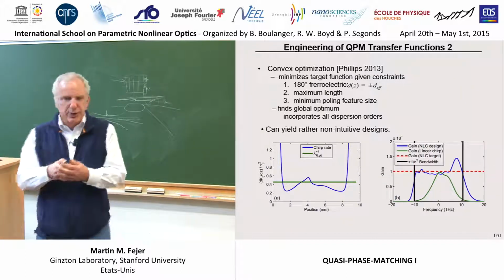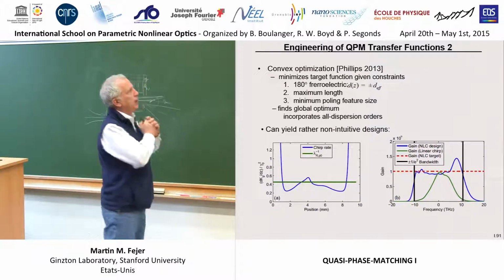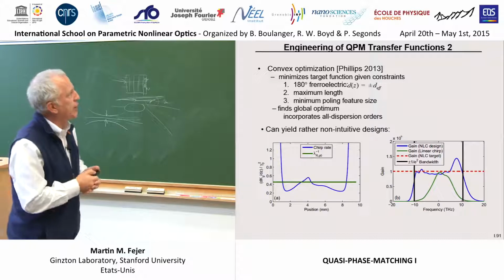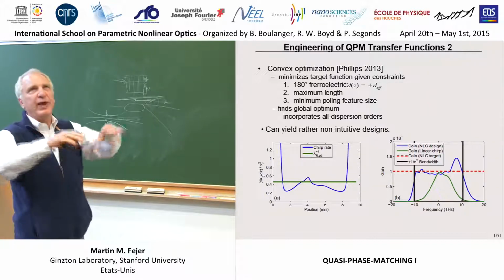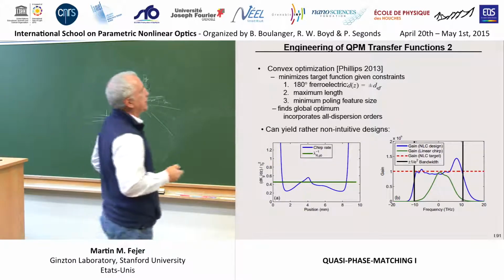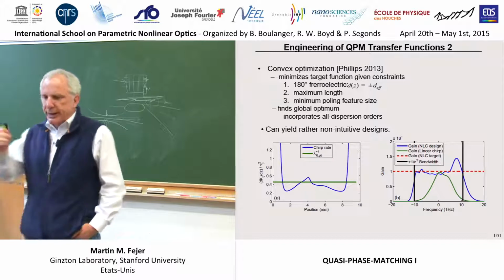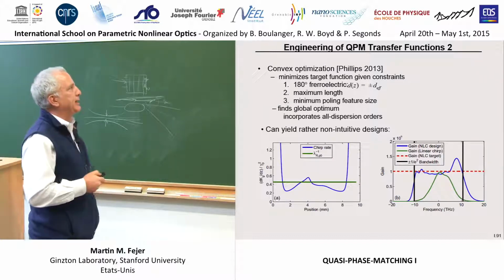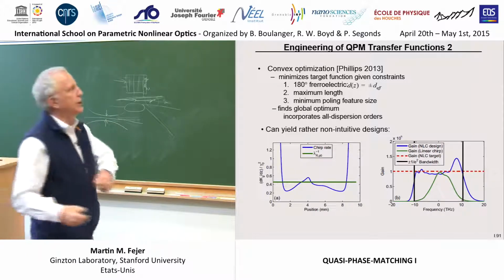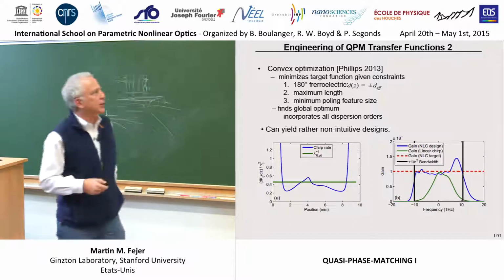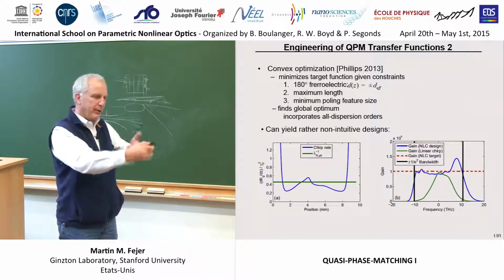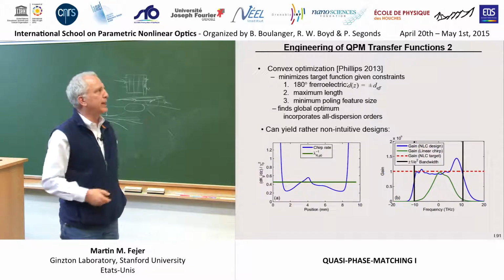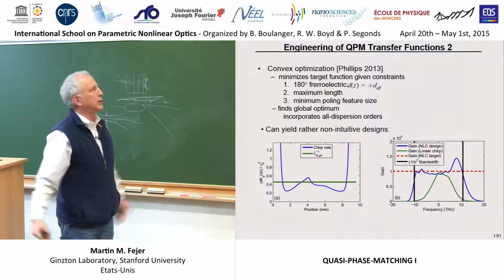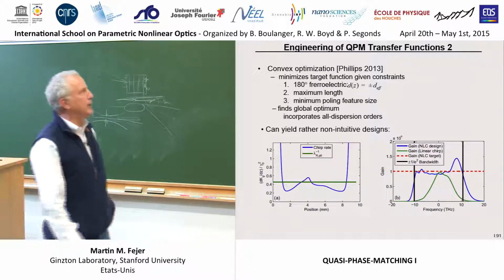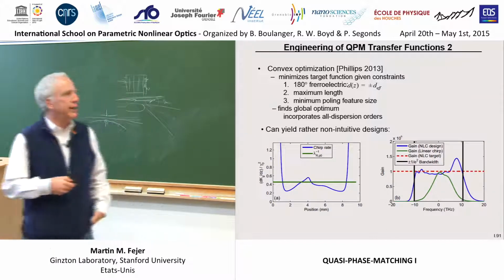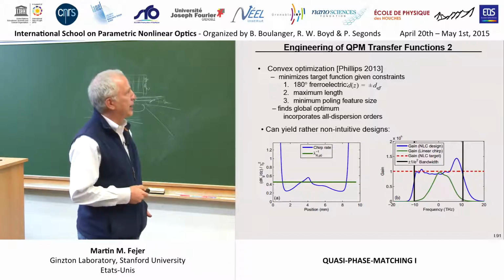Chris Phillips, who was a very good student who graduated from my group a couple of years ago and is now a postdoc with Ursula Keller, he showed that you could actually convert a large family of these grating design problems into ones amenable to convex optimization. And if you can make that mapping, then you can get absolute global optimum solutions if you've defined a particular target function and a set of constraints, like you can only make plus or minus gratings, you have a certain maximum length for your structure, you have a certain minimum poling size. You can find what is the best, globally best solution. There's standard software, something called CVX out there, that if you can define your problem in this fashion, you get that as a straightforward output.